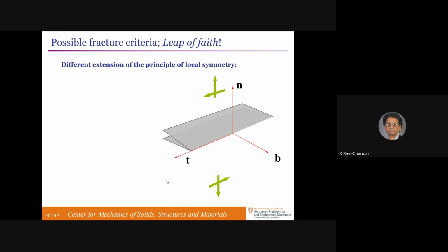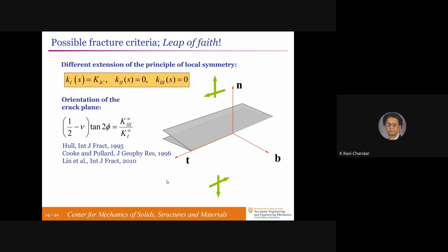So we need a new criterion. So here's the leap of faith. We made a different extension of the principle of local symmetry. Instead of insisting that only the mode 2 stress intensity on the tilted crack is 0, you say crack is not capable of shearing at all. So on the new crack surface, you should have both the mode 2 and the mode 3 stress intensity factors equal to 0, and you only have a mode 1 stress intensity factor. That must reach the fracture toughness of the material.